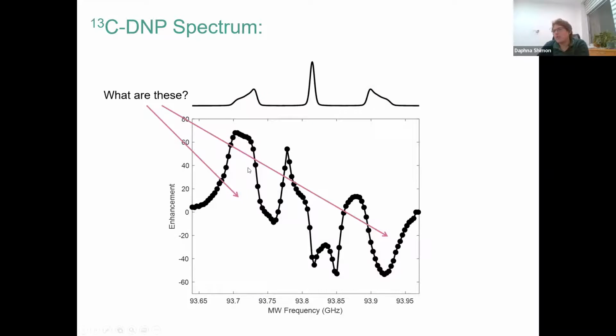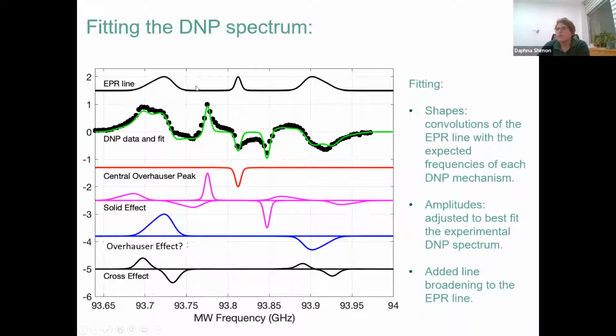So really the big question is, what are these big peaks in the DNP spectrum, and what's the mechanism that's coming from them? And so right now I'm going to just say that we'll call them the Overhauser effect, and we'll see a little bit later. But here is a fit of the DNP spectrum using shapes that I calculated for each one of the mechanisms, just by convoluting the EPR line with the expected shape that we think would come from each of the mechanisms. And so you see here at the center there's a negative Overhauser effect, and then on the sides would be solid effect from the narrow line, and also some solid effect from the two outer lines, cross effect, a small amount of cross effect on each outer line, and what we're here calling the Overhauser effect.